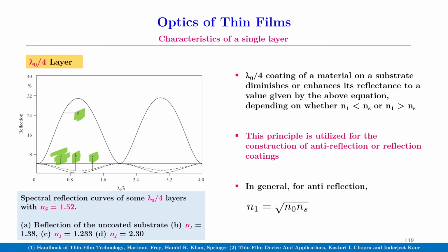We see a quarter wavelength thickness coating of a material on a substrate diminishes or enhances its reflectance to a value given by the above equation, depending on whether the refractive index of the film is less than or greater than the substrate refractive index, that is n1 less than ns or n1 greater than ns. This principle is utilized for the construction of anti-reflection or reflection coatings.